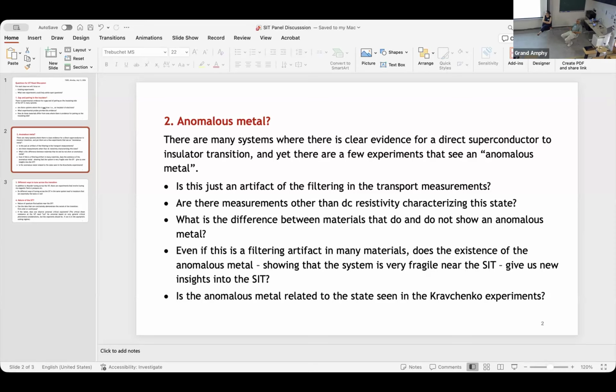Imagine that part of the sample becomes metallic, and then you just measure. Some parts are superconducting, so the conductance is better. Some parts are metallic. There is no path that shunts the... You said exactly what I wanted to say. Okay, so I want to hear your opinion about that. I have always thought about a very simple model first. If I have superconducting grains which are coated with normal metal, I will always see an anomalous metal, because at some point my superconductor will become zero resistance. All that will remain is the normal metal part, with finite resistance as you go to low temperature.